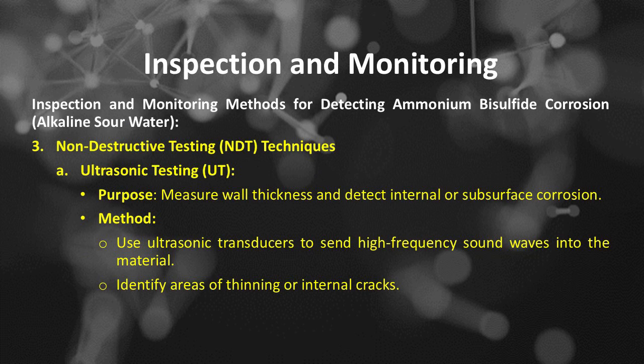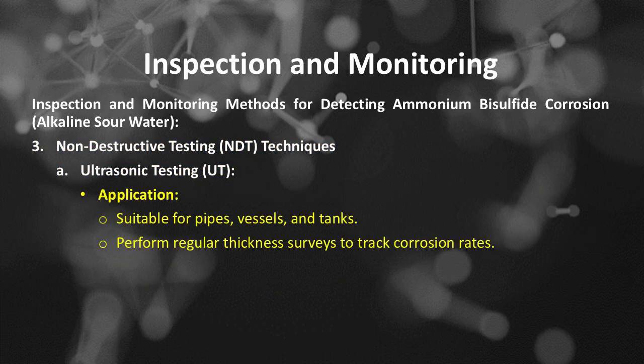Inspection and monitoring methods. Number 3 is non-destructive testing or NDT techniques. NDT. Number A, ultrasonic testing or UT. It is purposed to measure wall thickness and detect internal or subsurface corrosion. The ultrasonic testing method uses ultrasonic transducers to send high-frequency sound waves into the material. It works to identify areas of thinning or internal cracks. UT is suitable for pipes, vessels, and tanks; perform regular thickness surveys to track corrosion rates.